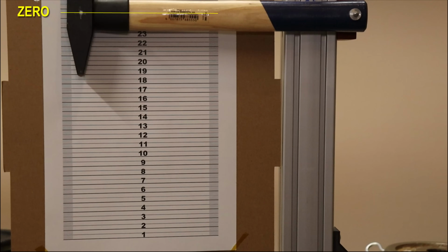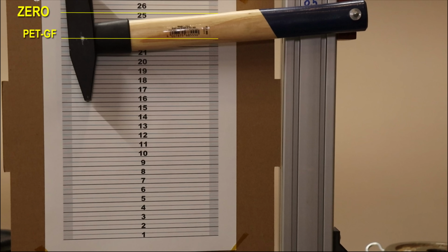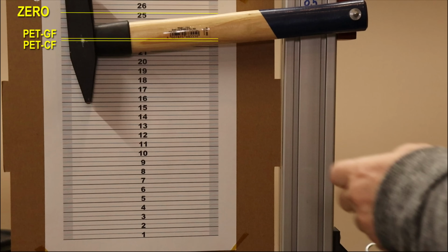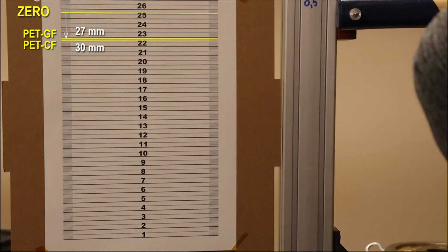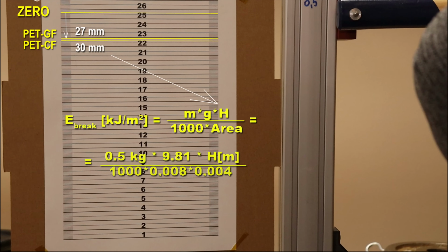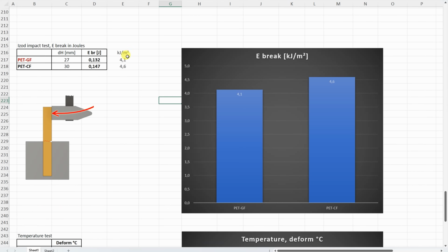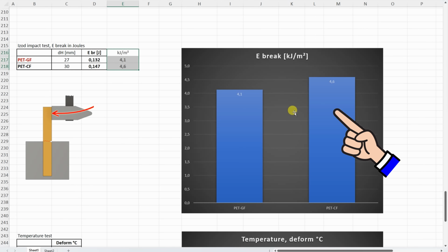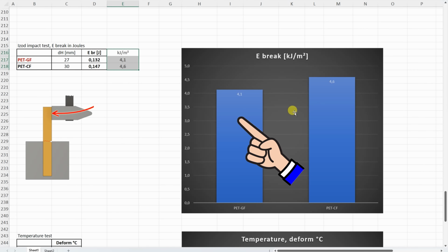This is the zero position of the hammer, and this is after breaking the PET-GF. And this is after PET-CF. And if I measure everything from the zero position, I am getting this difference in height, and I can calculate the breaking energy. This also means that the carbon fiber version is slightly tougher compared to the glass fiber, but in both cases these are quite brittle materials.